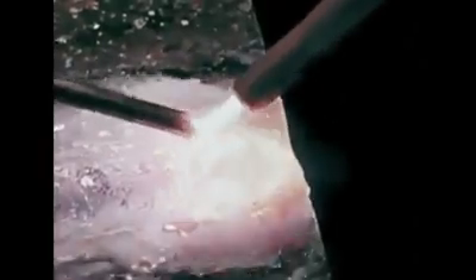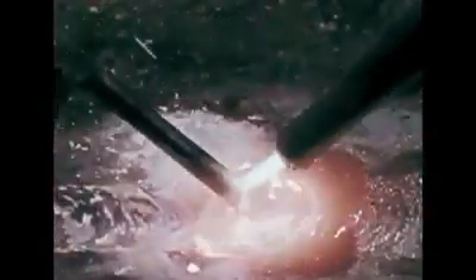Now we lay the second pass just as we did the first. Heat penetration and puddle control are just as important in this second pass as in the first. Both the sides of the V and the top of the first pass must be molten as you make the second pass in order to fuse completely with deposited rod metal. If the puddle grows too large, draw the flame away and let the puddle harden slightly before trying to move it further along. Remember that the weld bead will be the same width as the weld puddle. Keep the weld bead even in width while you are building it up.